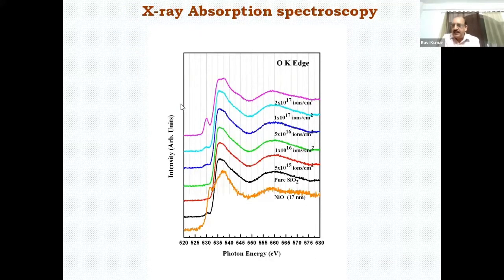Now the question is this: we again test these materials using X-ray absorption spectroscopy to understand whether the nanoparticles are interacting with the surrounding oxygen or not. If they interact with the surrounding oxygen to form oxides, then multiplet structures will form, which you can see in an element-specific technique like X-ray absorption spectroscopy using synchrotron. Here we have seen that we didn't see any nickel oxide structures.